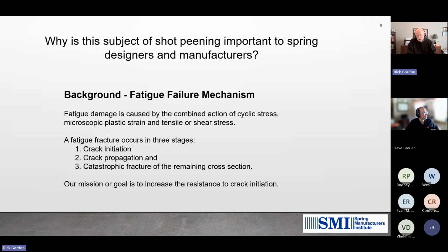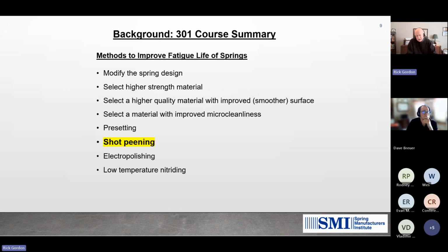So where do cracks initiate? Cracks typically initiate at the highest stress location. We learned that the highest stress location on a spring is at the surface, and for compression springs, the highest stress location is at the inside diameter due to the spring helix. So our mission or goal is to increase resistance to crack initiation. Again, in our fatigue class, we discussed several methods to improve fatigue life of springs. These include modifying the spring design, selecting a higher strength material, selecting a higher quality material, either with an improved surface or with improved micro cleanliness. We can preset compression springs, and of course, shot peening is one of the most important things we can do. Electropolishing and low temperature nitriding of certain grades. So today we've got the opportunity to explore shot peening.